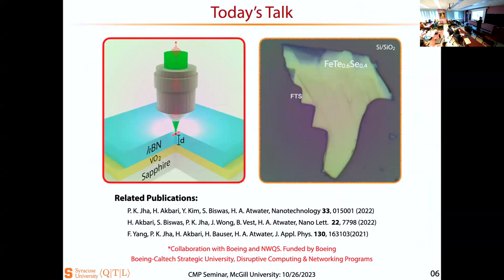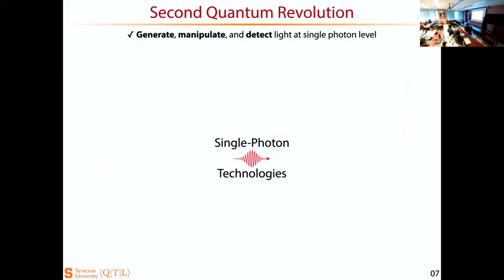Okay. Yeah, because the question which I asked is how we can extract where the color center is located. For the CVD growth sample, we know where it is. If it is 5 nanometer, I know it is somewhere in the middle. But if the sample is, let's say, 200 or 300 nanometer thick, we don't know where it is. It's a fundamental and also technologically important question to know where those color centers are. And I'll show you why.